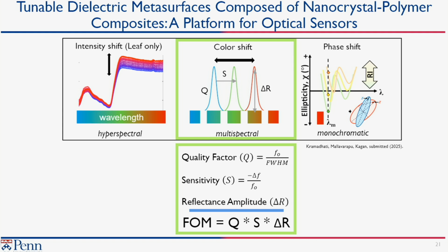We need them to be high Q, because if you can imagine, you want the resonance to be sharp so that if it shifts in wavelength, you can distinguish one from the other. That's where the high Q is important. You want it to be sensitive so that it shifts a lot relative to its width, to make it easier to detect. And this resonance has to have a large enough reflectivity so that the robot with the camera can actually go and see it. So we got better at this over time and looked at different processes to do this. And so we characterize a figure of merit as the product of these three in the design of the sensors that we create.